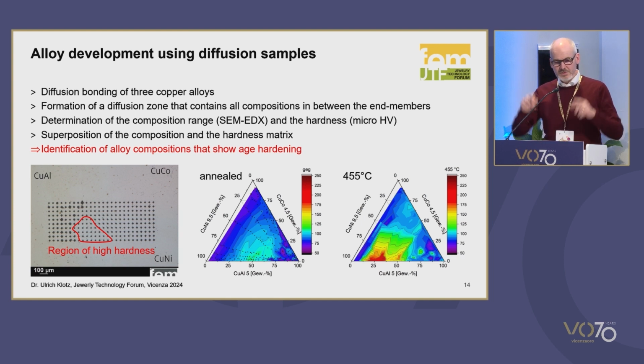And there are these 2 triangle diagrams. The left one is showing the hardness as a function of composition in the annealed condition. And the blue colors indicate that all the alloys are quite soft. Now in the right diagram, you can see that there are areas in red and yellow color.